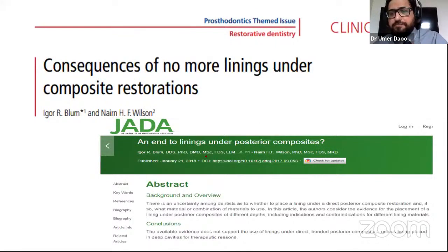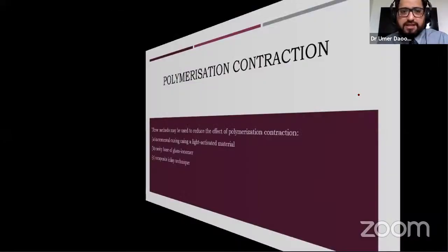I would really encourage the students to look into these two papers by Professor Igor Blum at King's College, where they argued that we do not need to line underneath dental composites at all, unless it's a therapeutic requirement. Let's say we are leaving behind a very carious dentine structure, and the clinician is not sure whether it is infected or affected. In that scenario, if there is a therapeutic reason, yes, we can think about lining using a resin modified glass ionomer. But generally, if it's a normal cavity with sound, healthy dentine, even if it is deep, it is not required to place a lining underneath a dental composite.